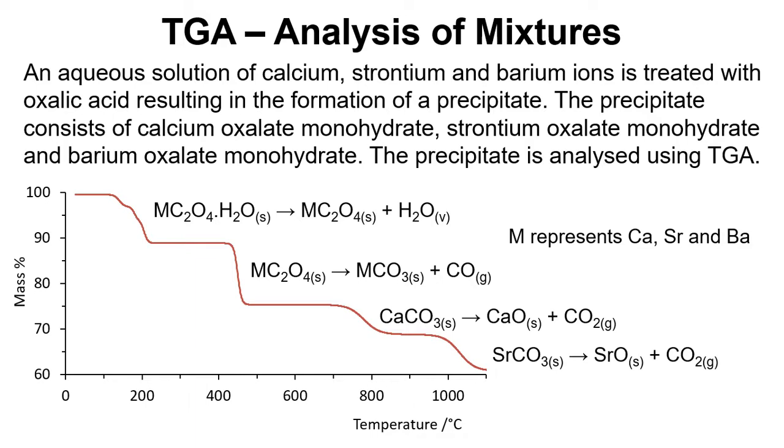Now the trace doesn't go high enough unfortunately for us to see the barium carbonate being decomposed because that happens at a higher temperature above 1100 degrees. And we've only got data up to 1100 degrees.